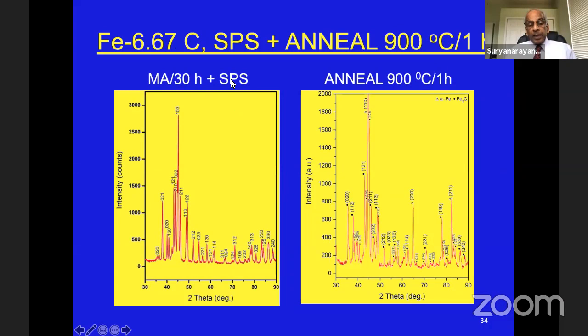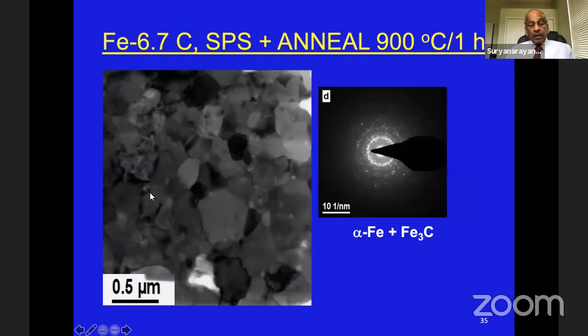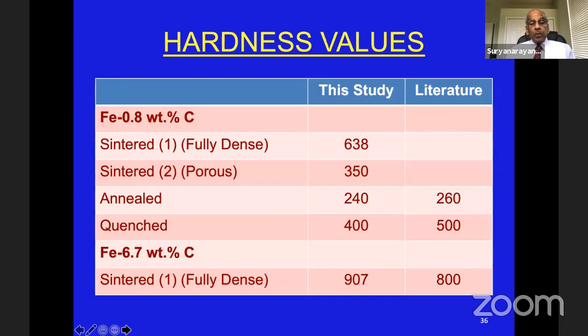But after SPS, if you anneal it also, again, like in the previous case, you can get very sharp peaks. And then because this is annealed at 900 degrees Celsius, some amount of alpha ferrite also has formed in this particular case. And if you look at the microstructure, again, you will see the distribution of grains, which are larger than in the previous case, but the diffraction pattern indicates ferrite and cementite, both of them present, but the amount of ferrite is relatively small in proportion.